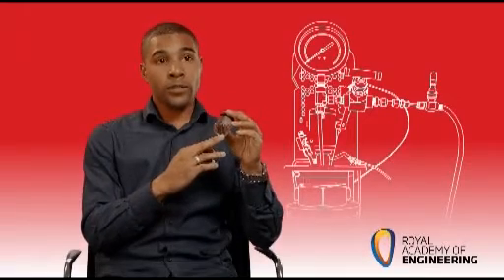So what the engineers do — as in myself — we put this into a high-pressure reactor and take it to quite high temperatures and high pressures. Under those conditions we can actually get water to degrade entirely the resin, and we end up with these loose fibres that you see in the bottom here.